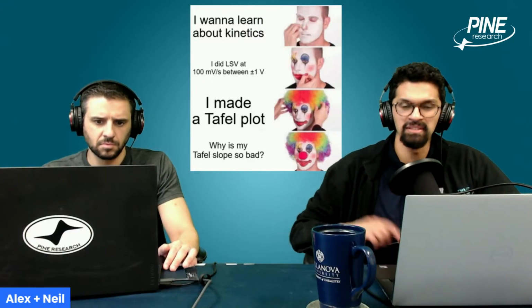But what you're saying is, at very low concentrations of electrolyte, the Bruce-Vincent method maybe doesn't work so well. So at high concentrations, where you're unlikely to get gradients in the electrolyte, you can use the Bruce-Vincent method to determine the transference number for the ions of your electrolyte. I'm looking through, and it's possible I have that entirely backwards. No, I'm not so sure.